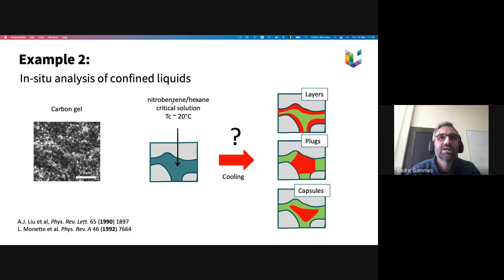experiments that we did with nitrobenzene and hexane solutions, which we put inside the carbon gels. So these are the type of materials, carbon aerogels, that are typically used in electrochemical applications because they're electrically conductive. And so we fill the pores with a solution of nitrobenzene and hexane. The interest of this solution is that it has a critical solution temperature around 20 degrees. So basically, if you're above 20 degrees, the two liquids are miscible, and if you cool it down, the two liquids can't stand each other.